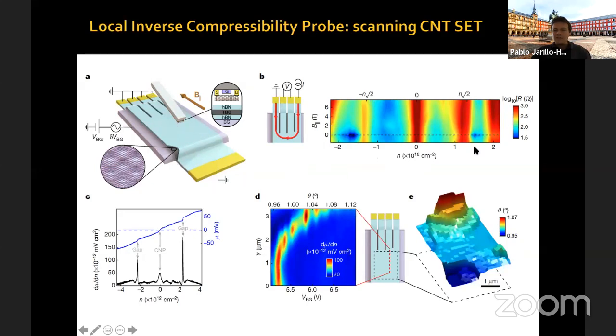And we can measure transport in our magic angle graphene sample, and we see correlated insulating states at 2 holes and 2 electrons per moiré unit cell and superconducting domes nearby. So this is the way the data look. What we measure is this trace, dμ/dn, this black trace. You can see that as a function of density, we have these 2 large peaks which correspond to the band insulator gaps at 4 electrons and 4 holes per moiré unit cell. Another peak at the charge neutrality point, because it's a region of 0 density of states, corresponding to the Dirac point of magic angle graphene, also a peak there.